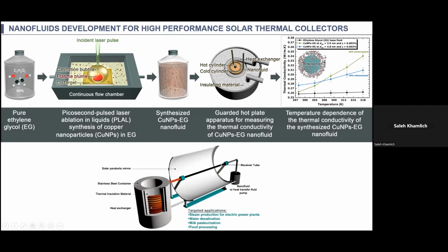The other nanoparticles, made by the 515 nanometer laser, show 30% enhancement. At the beginning, I was not happy with my colleagues because of the issue of this fragmentation, and the nanoparticles are absorbing the laser at 515. We were not happy, but after doing the analysis, we found that those nanofluids are the better ones.